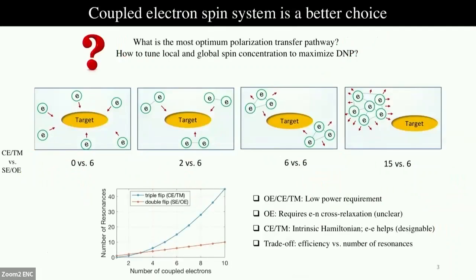In order to maximize DNP transfer from electron to the nucleus, what we need to do is tune our local and global electron spin concentration. If I have to give you a model, suppose you have 6 electrons and all 6 of them are isolated, then it would only be either solid effect or Overhauser effect that would be operative, but we will not have cross effect. On the other hand, if all of them are coupled, then we will have a lot of cross effect or thermal mixing resonances present. So it seems like a coupled electron spin system is a better choice in order to have improved DNP.